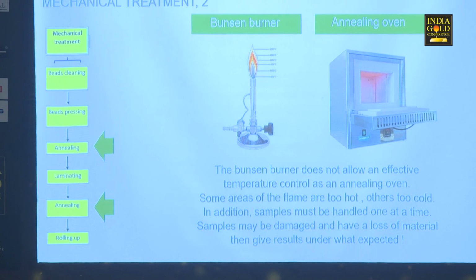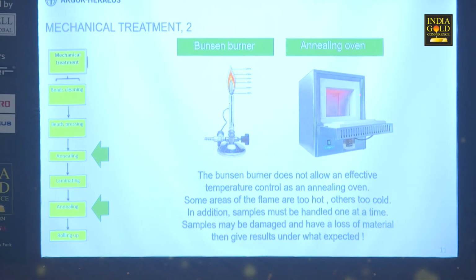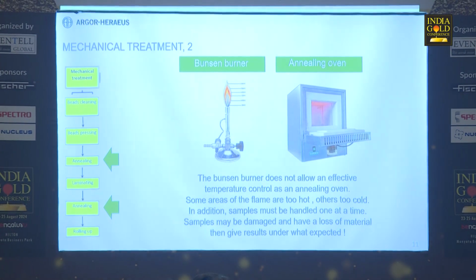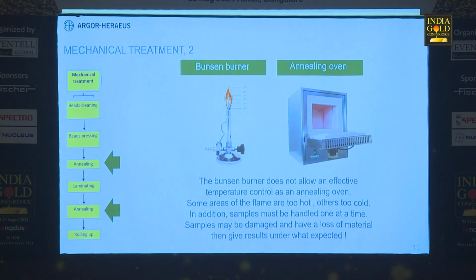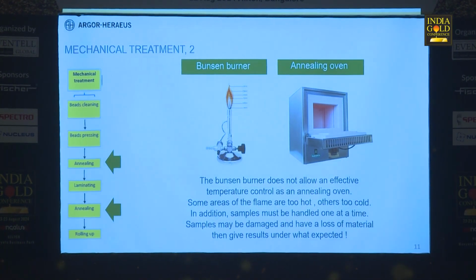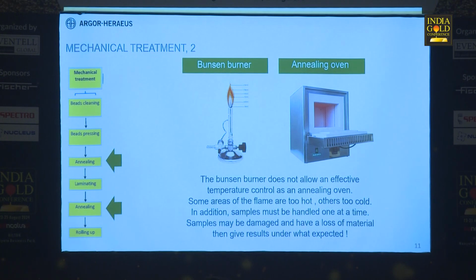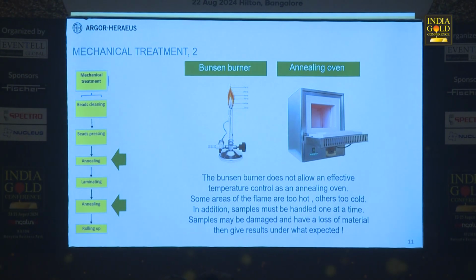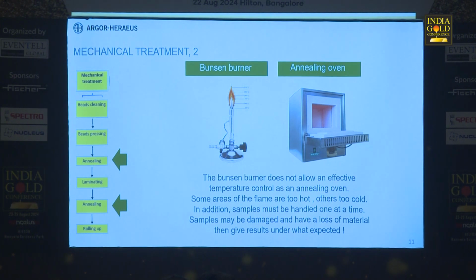An improvement that was done and can be done is the use of an annealing oven. We can set up a temperature, typically 800 degrees, something like that, between 640 and 800 degrees, and get a good homogeneity inside. And also we can use a sample tray. We can move all the samples at once and avoid any, let's say, human error.